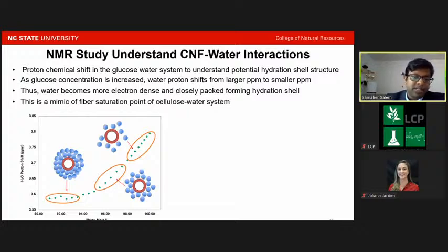So if you see the graph, this is a schematic, initially at 100% water, the water molecules are scatteredly arranged around the fibrillar surface. And as we go towards the saturation, we could see that the water proton shifts and it becomes more densely packed. Finally, at the saturation point, the water is really densely packed around it, forming a very strong hydration shell. And this hydration shell decreased the reactivity.